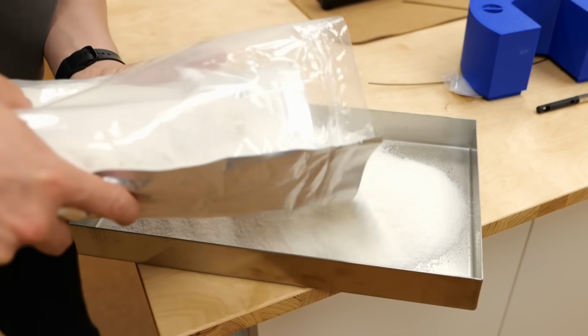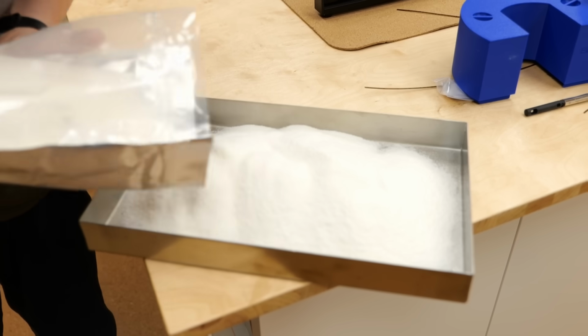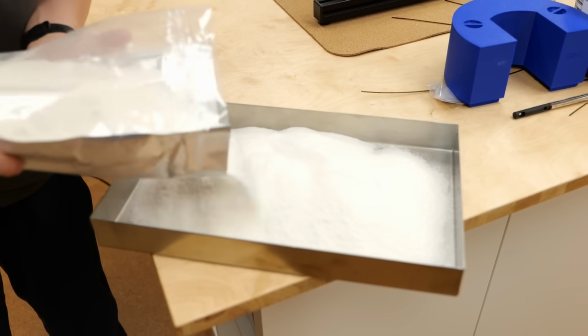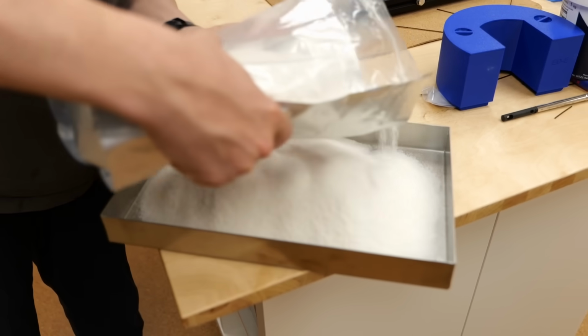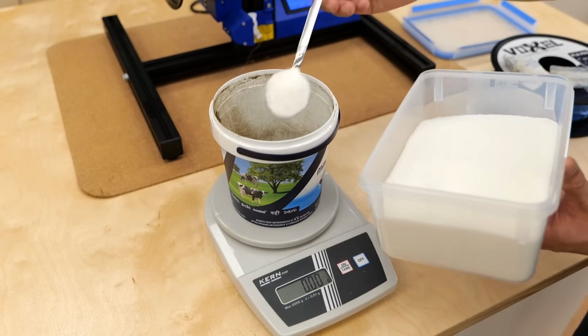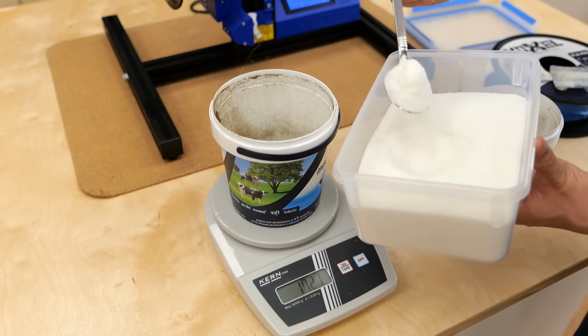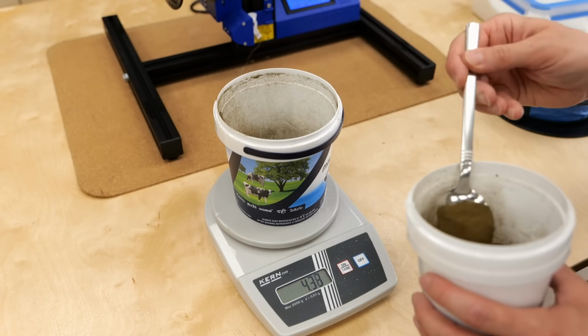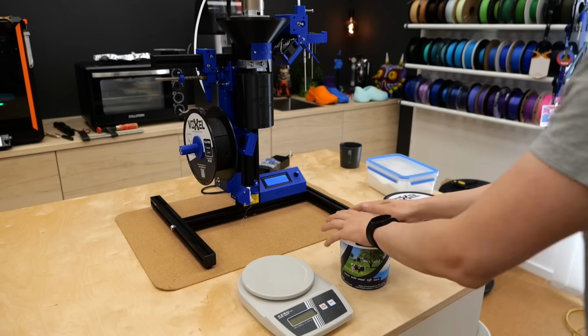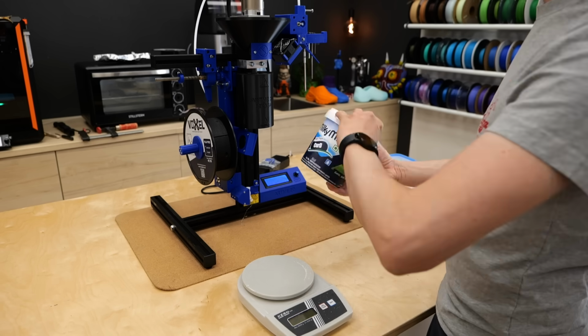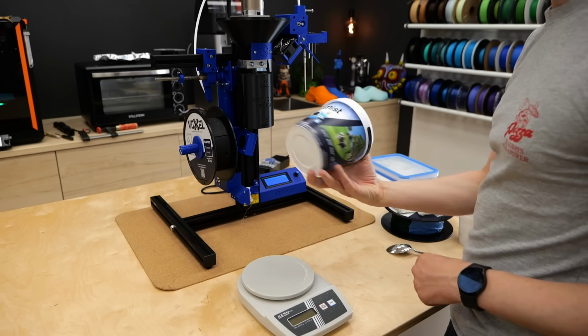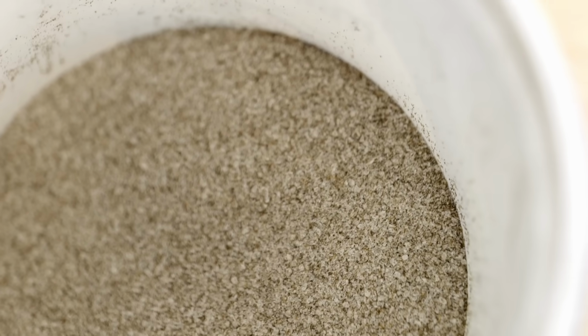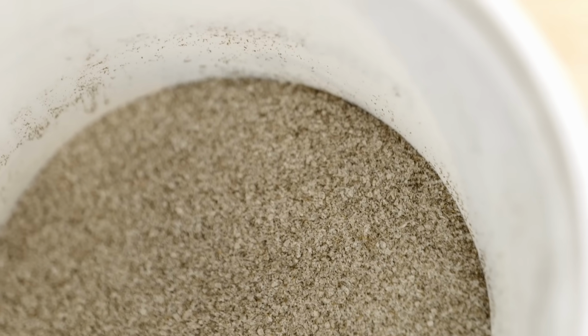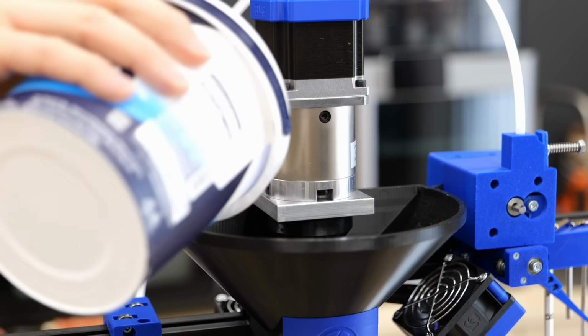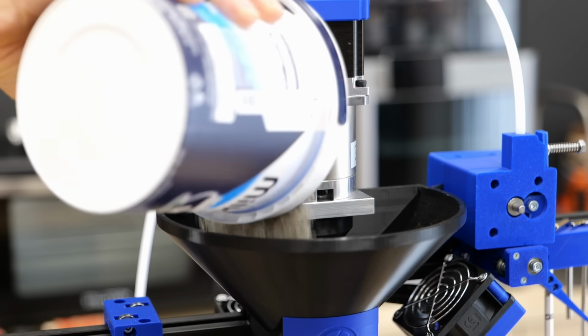And this might allow us to evenly mix both components before they go into the extruder to completely get rid of our agglomeration problem. I first tried everything and then created another mix, 150 grams of PLA powder and 7.5 grams of our sifted cow dung. After shaking it a little, I was already able to see that the mixing was way better and I had a very finely distributed filler between the PLA. So I loaded it into the hopper and started extrusion.